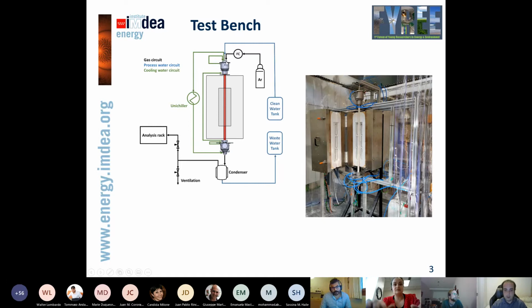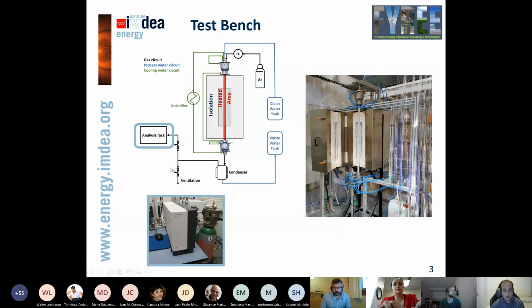Here you've got more or less the flow diagram that we use for this experiment, in which we pump argon into the system just to remove the oxygen from the process, and we also inject liquid water, because this liquid water will evaporate all along the tube, hopefully before reaching our reacting bed. Then this flue gas is condensed, and we remove the water and get to an analysis stage that for this experiment basically consists of a micro GC. As you may imagine, we're placing our bed at the bottom of the reactor, so that most of the water is evaporated by the time it reaches our reacting bed.